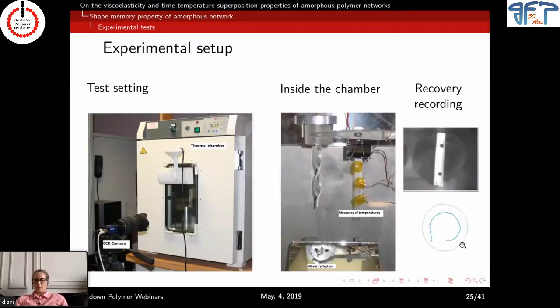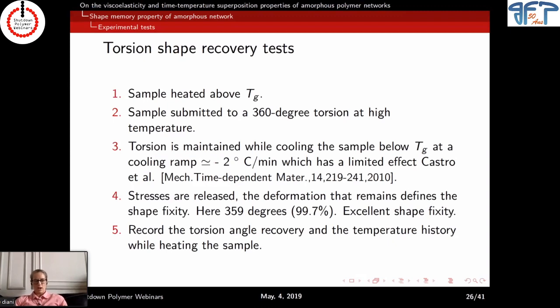Okay, so for the torsion, we heated the sample above the glass transition, applied a 360-degree torsion at high temperature, cooled it down, and looked at the shape fixity, meaning how much the material recovered after we released the stress at low temperature. And it was excellent because, applying 360 degrees, we ended up with 359 degrees of rotation. And then we recorded the torsion angle recovery and the temperature history while heating the sample.